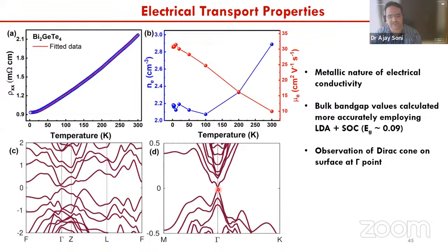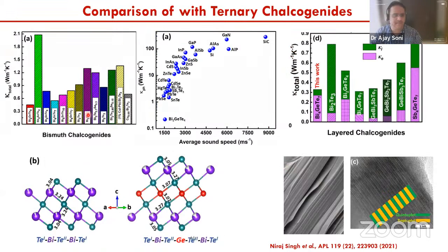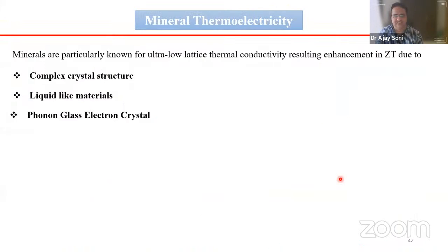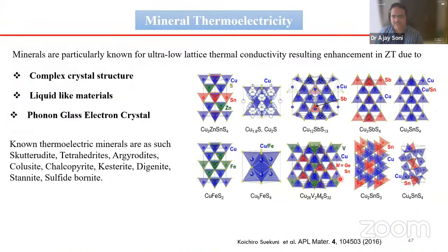So the surface calculation shows that there is a Dirac cone. And these materials, because of their layered structure, have a high anharmonicity, a very high Grüneisen parameter, and that can lead to very poor phonon thermal conductivity. These materials are very exciting to work on in thermoelectric research. And some aspects of complex structures we also work on.